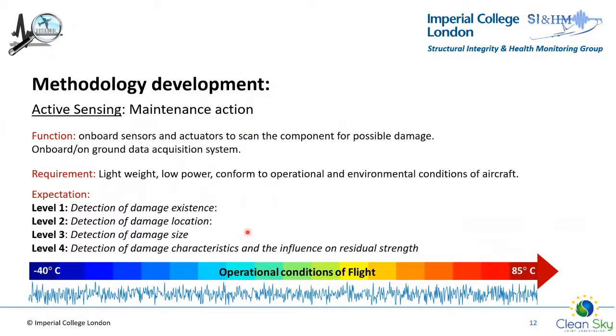Level 3, detecting also the size and severity of damage. And level 4 is really going towards prognosis, to say, okay, what is the influence of this damage on the residual strength of a structure. As you can see, as you increase the different levels of the intended function of your active sensing, you also increase the complexity of your SHM system, and the number and location of sensors must also be optimized for the different levels of intended function that have been developed.